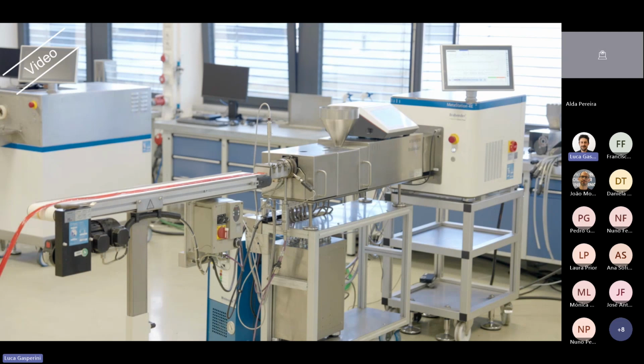The only limitation of Raman in an extruder is if the sample is very fluorescent, then you would need a different wavelength, a different wave range. Otherwise, you will not get enough intensity. Or if the samples are super black. So this is the only main limitation. If you have very dark samples, for example, you would not get a response from Raman.